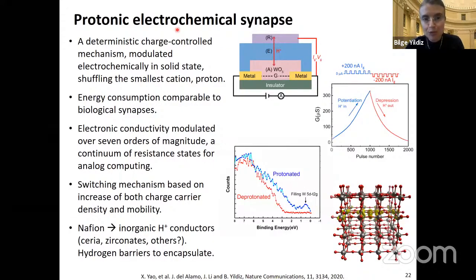So in summary, on this protonic electrochemical synapse, I've shown to you that we could come up with rather a proton battery, which deterministically injects protons into and out of an insulating layer that modulates its electronic conductivity, that gives us the ability to potentiate, increase the conductance, increase the synapse strength, and depress, weaken it. And we can do this with a very low energy consumption, as I have shown to you, comparable to biological synapses, thanks to the fast mobility and low barriers needed to move protons.